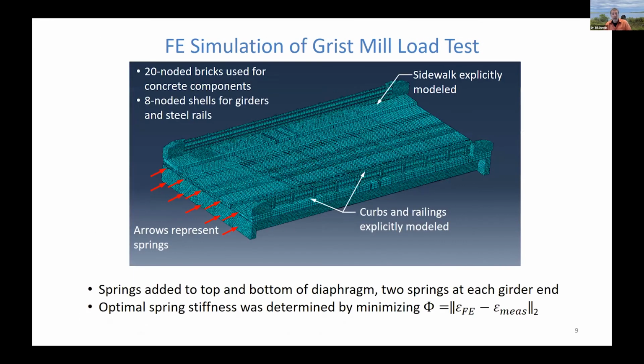So we took a closer look at this. We built some really high fidelity finite element models using solid elements to discretize all the concrete components, explicitly modeled the girders with shell elements. We modeled steel railings, integral curbs, the sidewalk, all these non-structural sources of stiffness. We also put at those concrete diaphragms at each end of the bridge some linear springs that would allow that to capture that rotational restraint. So as the bridge deforms, the ends rotate, those springs are activated.